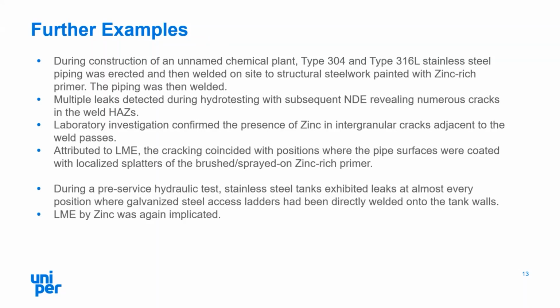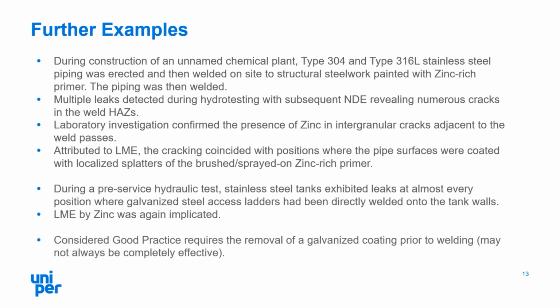A third example was during the hydraulic test of stainless steel tanks, where there were leaks detected at almost every level where a galvanized steel ladder had been welded directly onto the tank walls. Once again, liquid metal embrittlement was implicated. It's generally considered good practice, whenever welding galvanized components, particularly to stainless steel, to require removal of that zinc coating from the component prior to welding, although noting that it may not always be possible to completely remove that coating effectively from the surface. That may still be a slight residual risk.